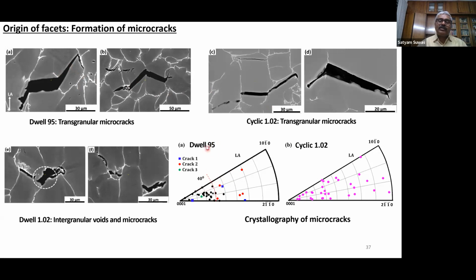And we could see that for the dwell subjected material at 95% loading, some cracks were far from the basal orientation, but most of the cracks were within a 40-degree range of the basal orientation, right? And in this case, of course, this was quite spread. The crack initiation for higher cyclic loading was very strange in this case.